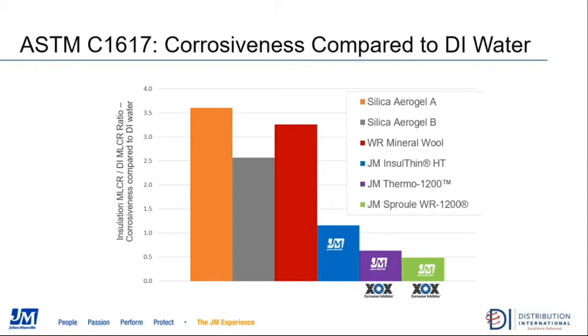As you can see by the orange, gray, and red bars in the chart, insulation materials such as mineral wool or silica aerogel have a corrosion rate ratio significantly higher than that of DI water, on the order of 2.5 to 3.5 times higher than the rate of the DI water samples. Whereas the Johns Manville Insulthin, which is the microporous thin blanket material, has a corrosion rate very similar to that of DI water, as represented by a ratio very close to 1.